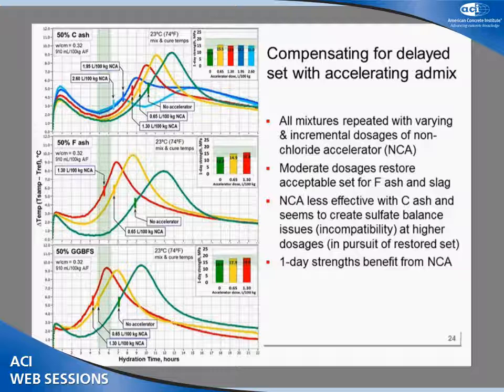At 50%, even a maximum dose of this non-chloride accelerator doesn't quite get us in the band for target set times, and now we see some incompatibility occurring, or we suspect that's what's occurring. To support that, our one-day strengths are not improving as we go to higher dosages of the chemical admixture accelerator.